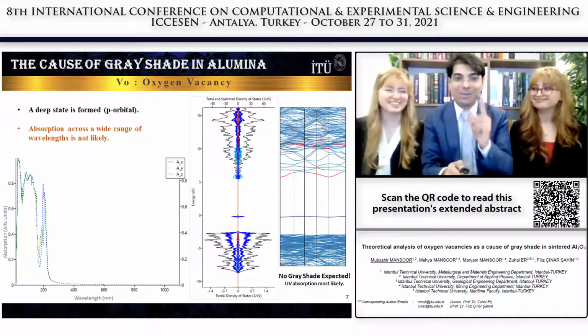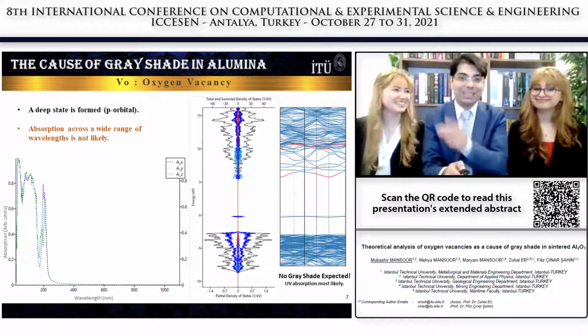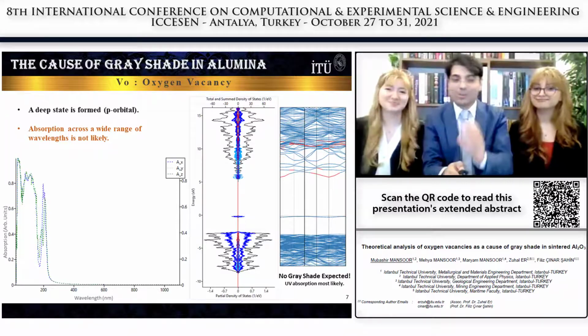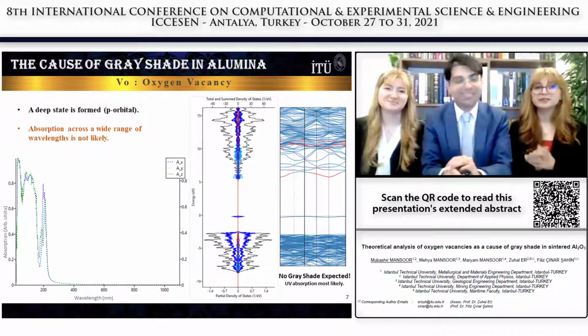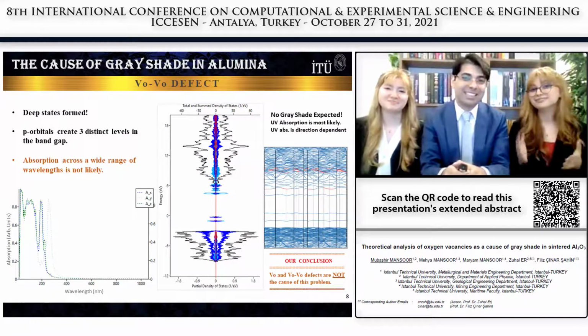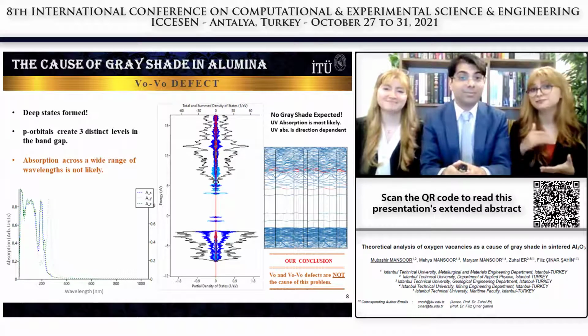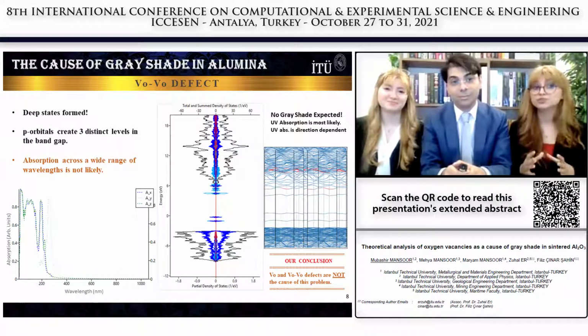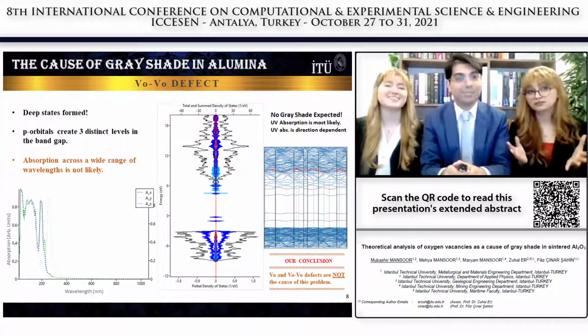So that's an important thing to remember. And here is the calculated absorption spectra as we would expect, shown here. Exactly. So when we look into an extended vacancy defect or a di-vacancy, the spectra is different because of the three allowed states in the band structure. We do have a red shift of the absorption edge in our calculated UV visible spectra, but the absorption is still in the ultraviolet region, this time in long wave UV.